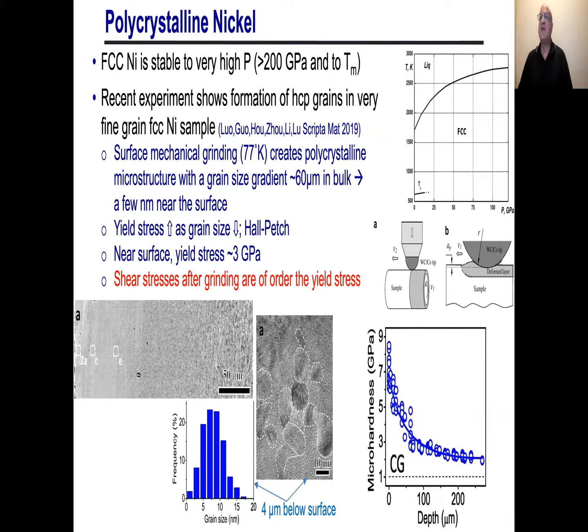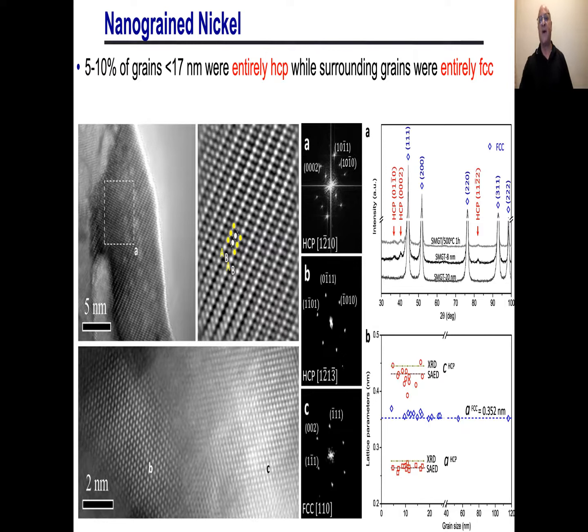Okay, so what they're showing here on the upper left in the high resolution TEM image is a region of the material, and if you go in and look at the atomic structure, you can show that it's hexagonal, or if you do the electron diffraction from it, you also see all these peaks which you can index as hexagonal. Here's another region here. This is a 2 nanometer scale, and this grain here, an entire grain, indexes to a hexagonal close packed material, and the grain right next to it indexes to an FCC material.